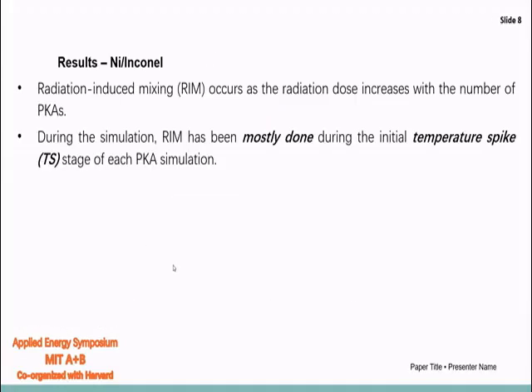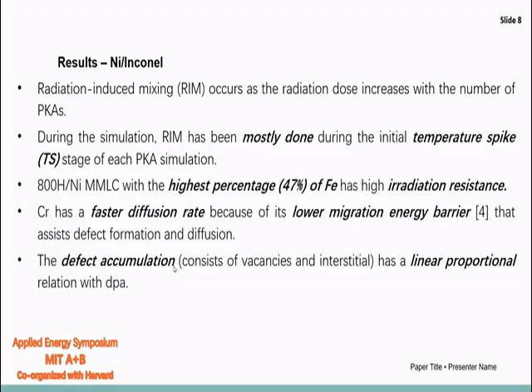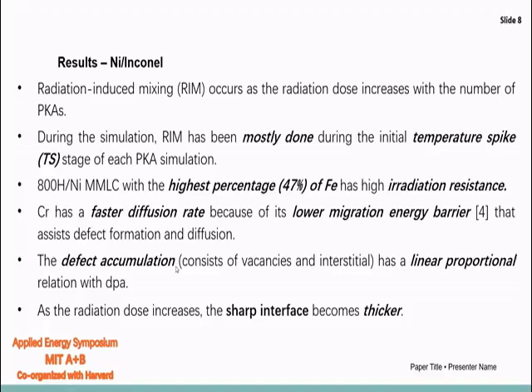So these are the results we can summarize from the findings of our study. Radiation-induced mixing occurs due to the radiation, as the radiation dose increases, and the radiation dose increases with the number of primary knock-on atoms. During the cascade simulation, radiation-induced mixing is mostly done during the thermal spike stage of the cascade. And from the parameters that we have got in our simulation, we can say that the 800H nickel multimetallic layered composite has a very high radiation resistance, and it has the highest percentage of iron among all the structures that we have used.